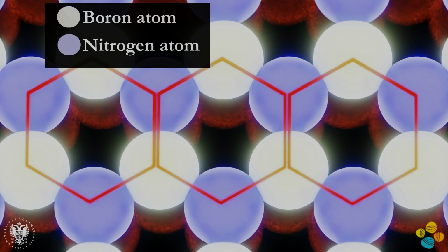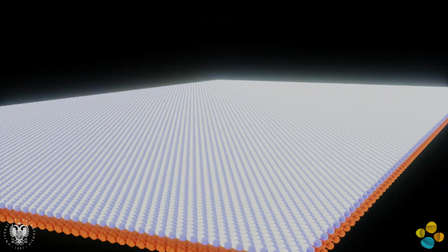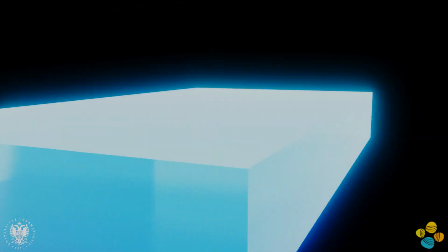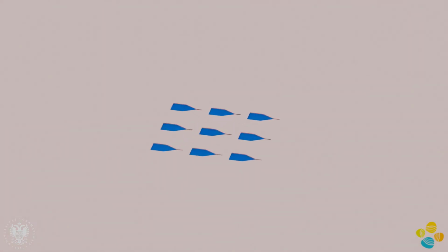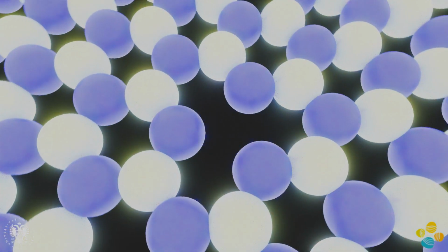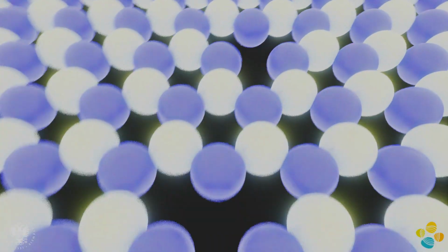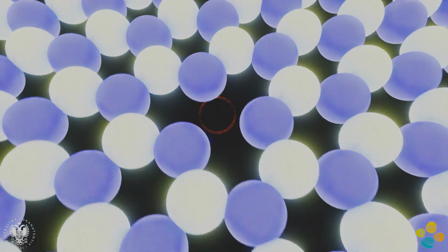After that, we used a sheet of commercially available hexagonal boron nitride and transferred it on the bottom electrodes. Finally, top electrodes, similar to the bottom ones but rotated 90 degrees, were deposited to form memristor devices. The hexagonal boron nitride synthesized using this method contains some native defects, and we consider them in our simulation study.